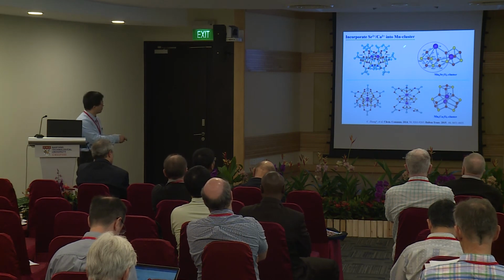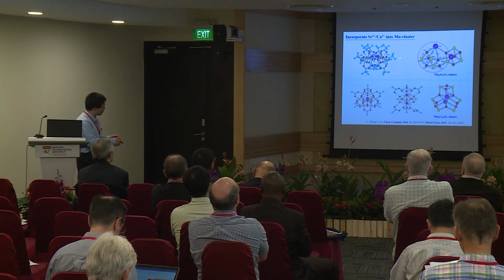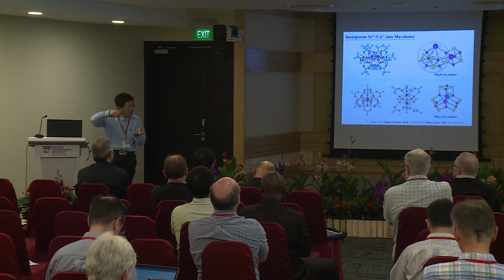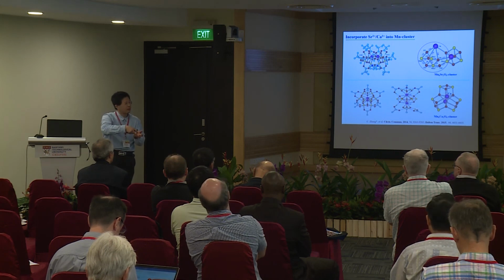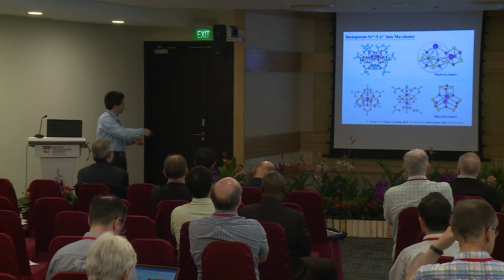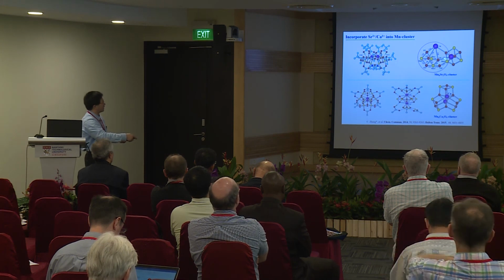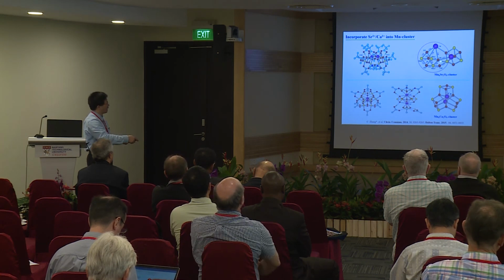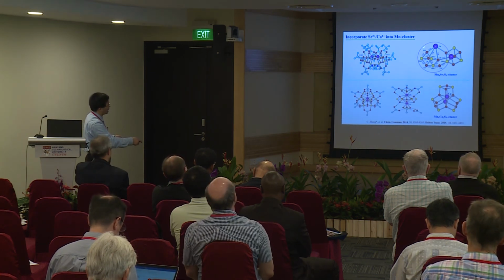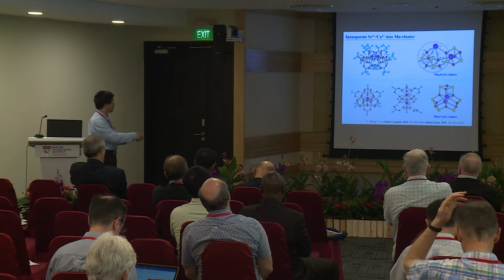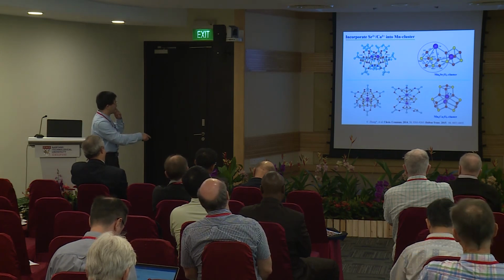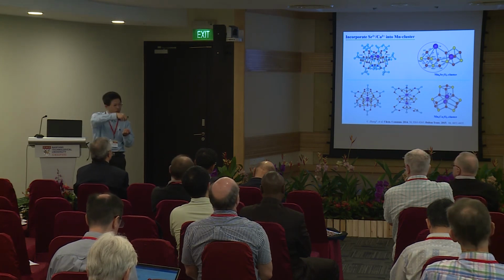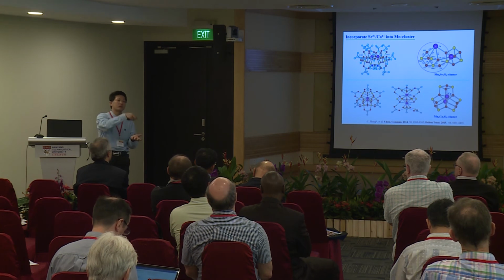Almost immediately we got this compound, because the most difficult thing is how to put the calcium or strontium into the manganese cluster. When we had the idea, we immediately got this compound. In the circle, you can see it looks very similar to the OEC. There are 4 manganese and strontium and all the types of bridging oxygen. At the same time, we can get another sample with calcium. So we can solve the problem of how to insert the calcium into the manganese cluster.